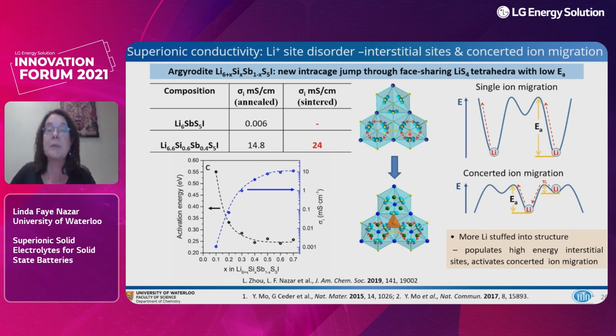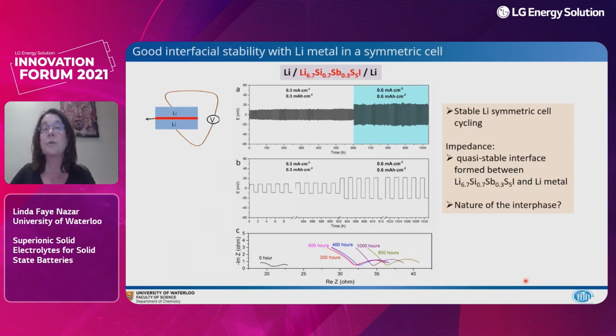And so the point is, here is the stepping stone position, and we have now stuffed it because we've populated this site because we have forced lithium into the lattice. And so we go from a situation where we have sort of single ion migration and a more limited step where one ion has to make a hop to the other cage, to a concerted ion migration because we've now populated a higher energy site, which is the stepping stone site. And so that overall lowers the activation energy and pushes this concerted migration process where the lithium from one cage will push the stepping stone lithium out into the next cage. And this concept of concerted ion migration has been nicely highlighted by Yifei Mo in a few of his recent publications. So this is, we think, a very, very important strategy for moving forward in these materials in general.